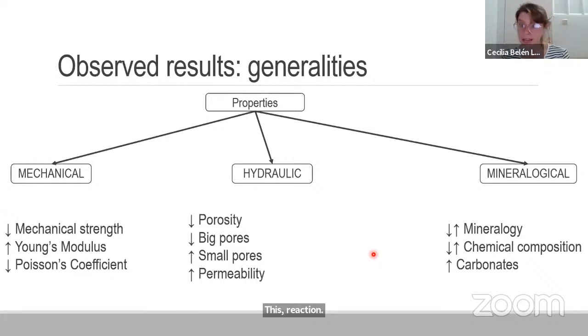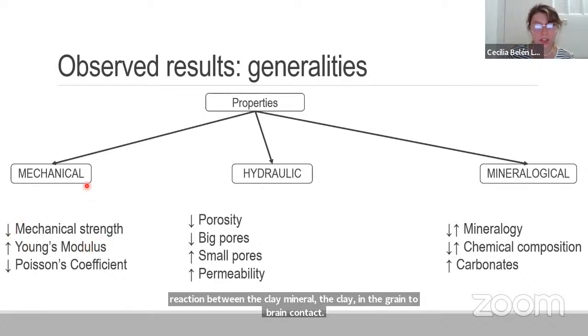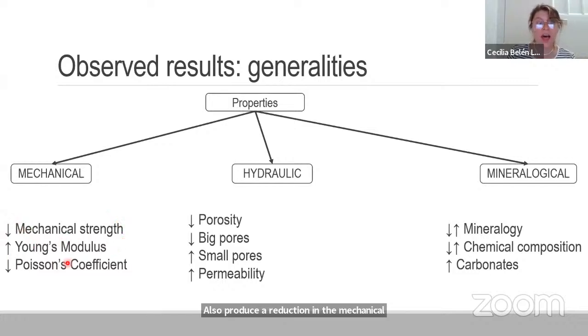This reaction between the clay grains in the grain-to-grain contact also produced a reduction in the mechanical strength and an increase in the Young's modulus.